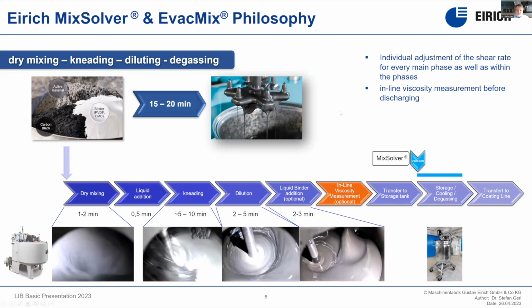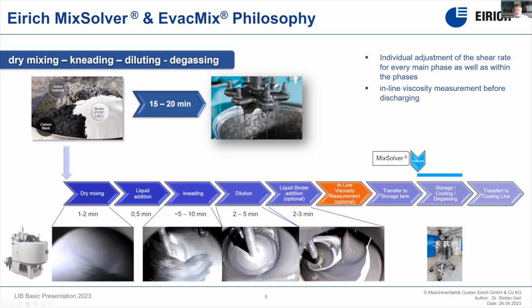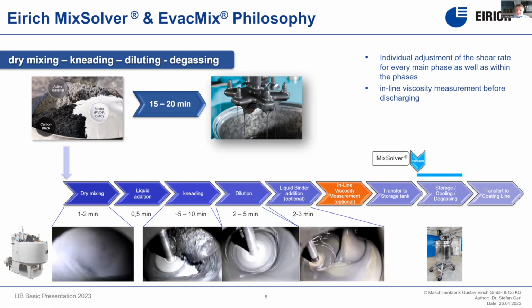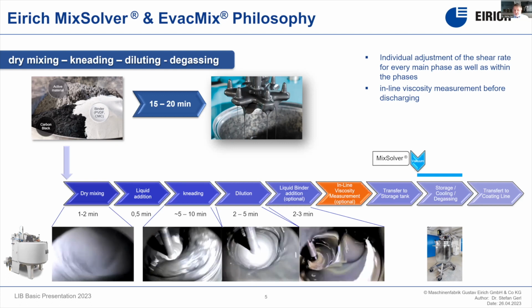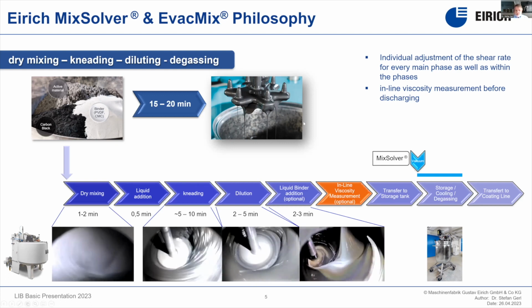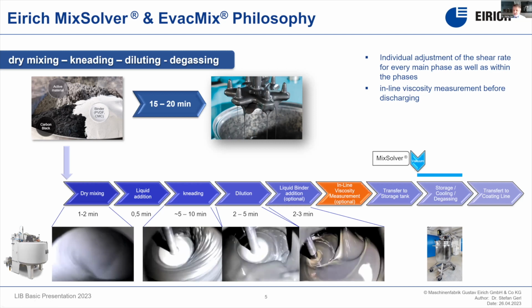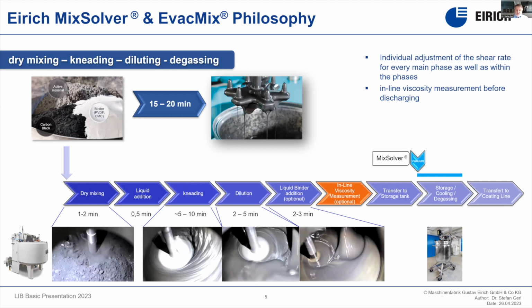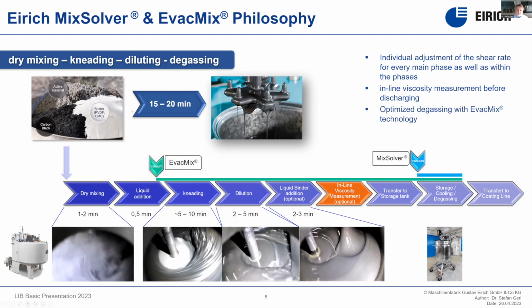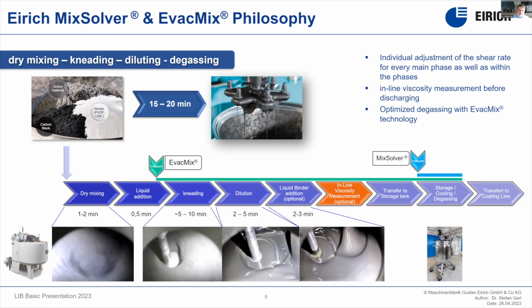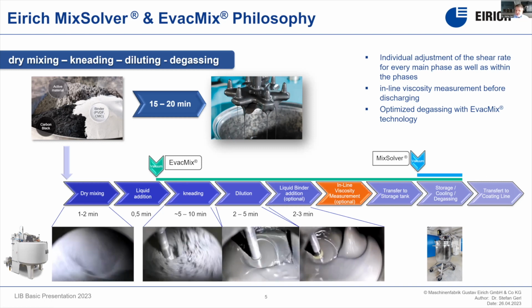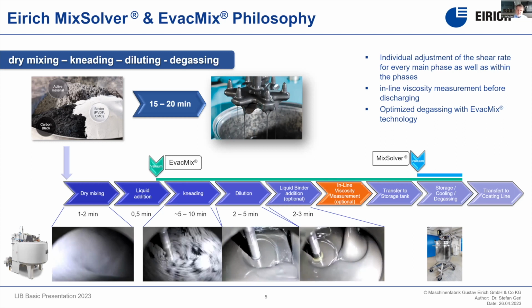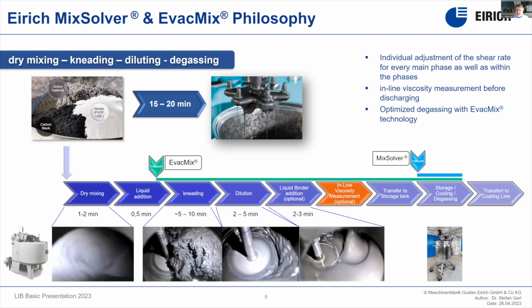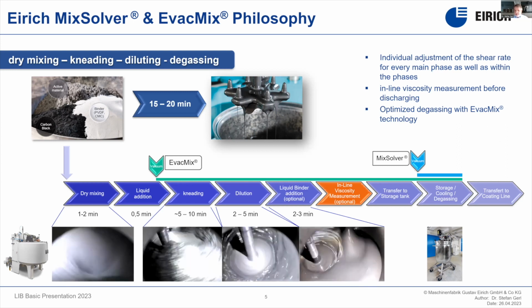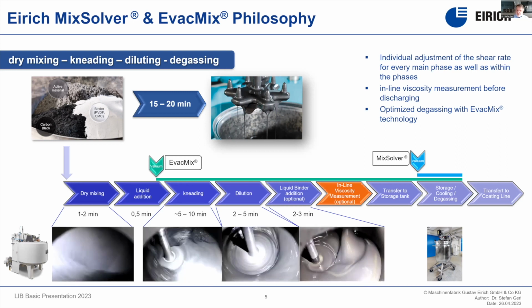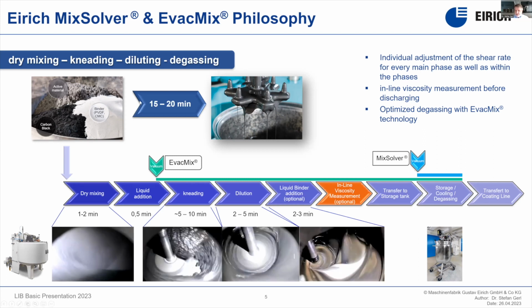We have different options. With a non-vacuum machine, we typically apply a vacuum in the storage and degassing tanks downstream of the mixer, which is a little bit the cheaper version. Some products don't need vacuum application during operation. On the other hand, with our EvacMix vacuum technology, we apply vacuum in the final phase of the first liquid addition, doing the kneading already under vacuum, so that we don't incorporate any gas or air from the very beginning. And by this, we can make sure that we have a 100% degassed slurry already at the final stage of preparation.